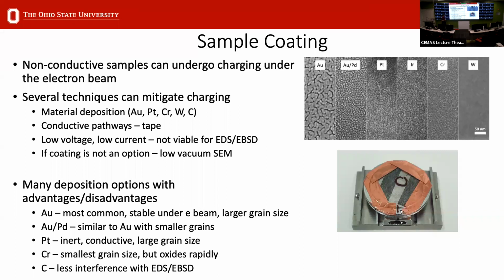Carbon is also very common, and this is actually very useful for TEM as well in a lot of cases. I'll discuss it a little bit more later, but if you're trying to do electron backscatter diffraction, you can't put something like gold on your sample because that'll interfere with your diffraction backscatter signal. So you would use carbon.